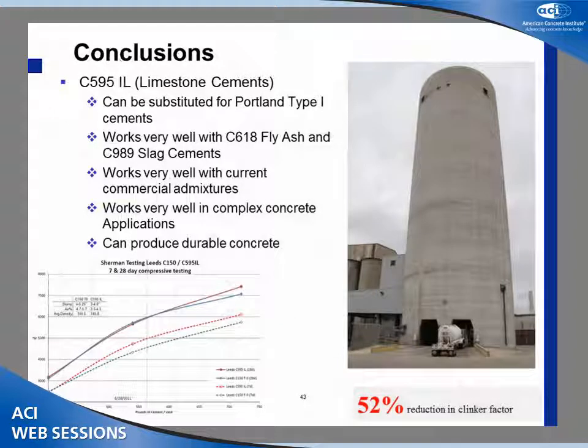Okay, so here's some conclusions. Here's the finished silo. You can substitute limestone cements wherever you would use a type 1 cement. Works very well with fly ash, class F fly ashes. Works well with admixtures because we tried lots of different admixtures and saw no big issues. Works very well in complex structures. This was a very complex structure, worked very well. And we can produce very durable concrete.